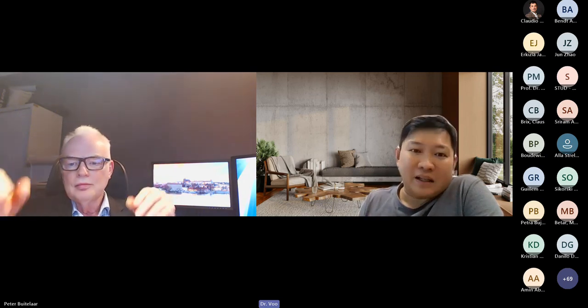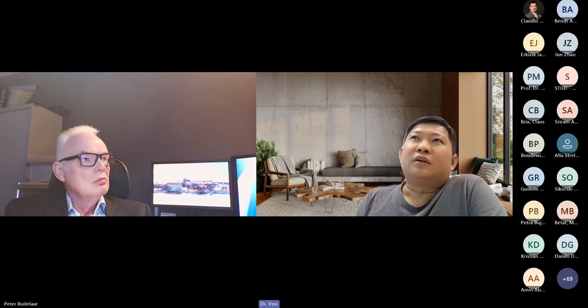Okay. So far, from our years of experience and with the number of bridges we have constructed, I put it in very simple layman's terms: if a steel composite structure or steel bridge can be used, then these UHPC structures are generally about 20 to 30% heavier compared to steel structures. So if steel structures can conventionally be used, definitely this is also not much of an issue because the mass of inertia is still higher than steel. So far there's no complaint whatsoever regarding the vibration or the dynamic response of these structures, whether for footbridges or for traffic bridges. That is our experience.